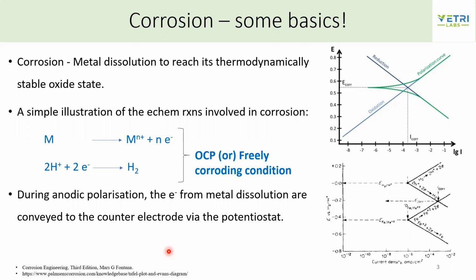In this process, as the metal undergoes dissolution, the electrons that are generated get consumed by another reaction. Shown here is a simple electrochemical reaction involved in metal dissolution: we have metal dissolving as M^n+ and n electrons. Since we are discussing hydrogen evolution in this paper, I have written 2H+ plus 2 electrons gives hydrogen. But depending on whatever system we are looking at, this can be different, it could be oxygen reduction reaction, or it could be reduction of another metal. It just depends. So let's stick to hydrogen evolution here.